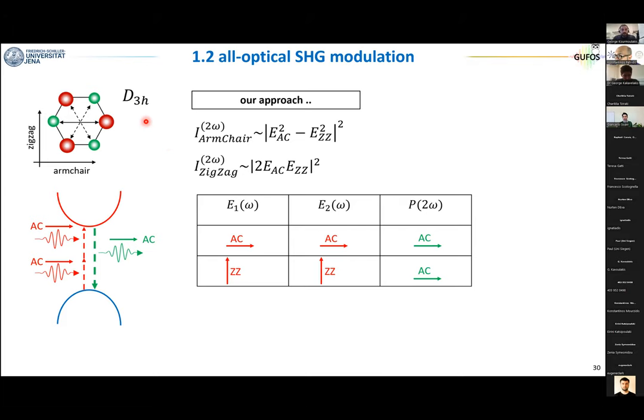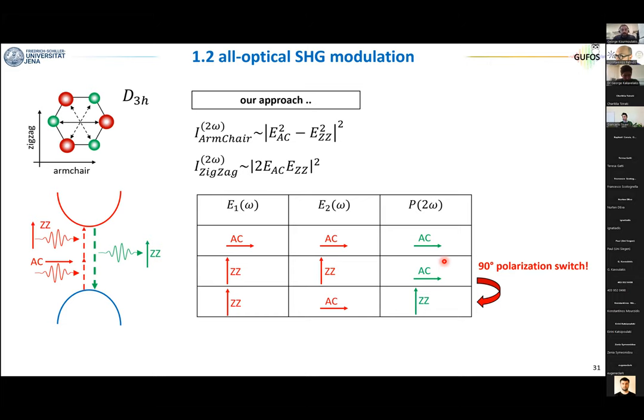Now, if you take this point group and look at what happens to the second harmonic, it turns out that if the two photons that contribute to your second harmonic signal are both aligned along the armchair or both aligned along the zigzag, then in both cases, your second harmonic is emitted along the armchair direction. However, if you split the two photons that generate the second harmonic, one along armchair, one along zigzag, then your second harmonic will rotate by 90 degrees and will be emitted along the zigzag direction.